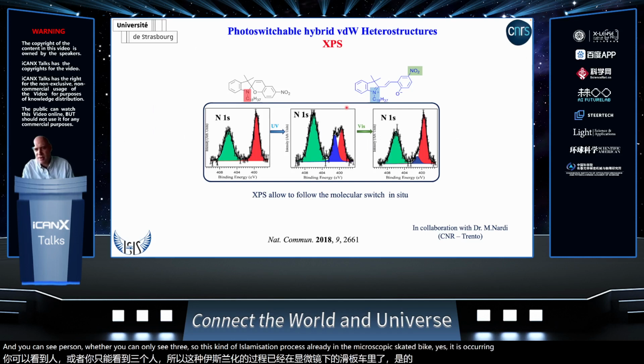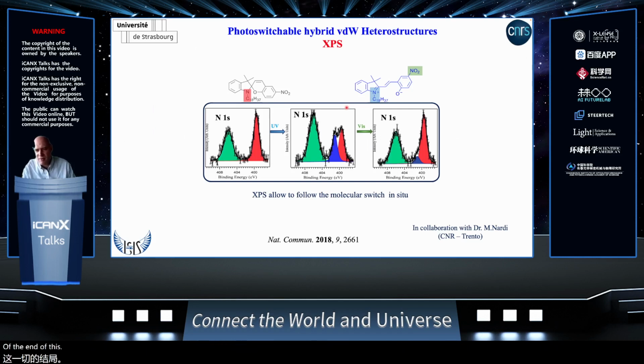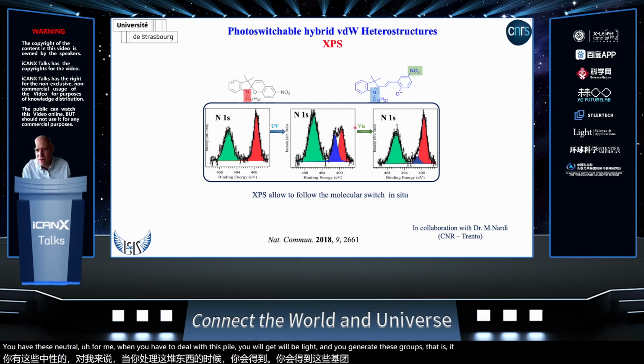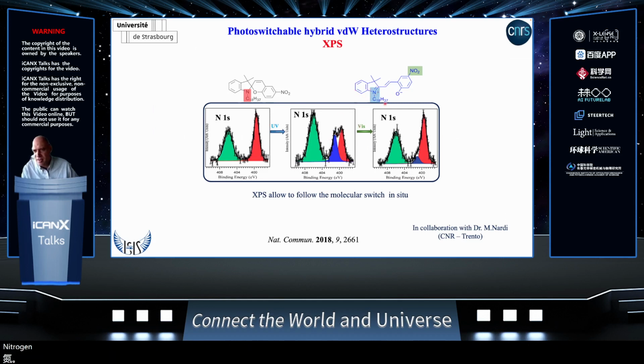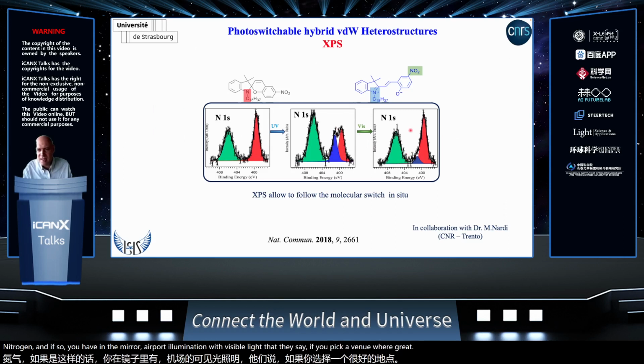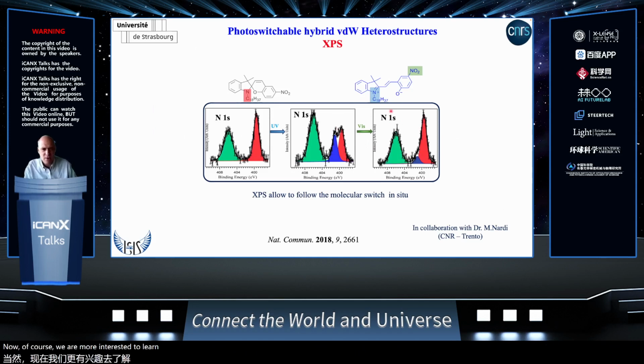This is occurring on the monolayer of this molecule that is physisorbed on the basal plane of graphite or even CVD graphene. Monitoring the N1s peak in the XPS spectra, you have this neutral form in red when you have the spiro. You irradiate with UV light and you generate this blue peak that is a fingerprint of the positively charged nitrogen that you have in the mero. Upon illumination with visible light, this blue peak vanishes to a great extent, proving the reversibility of this kind of switch.